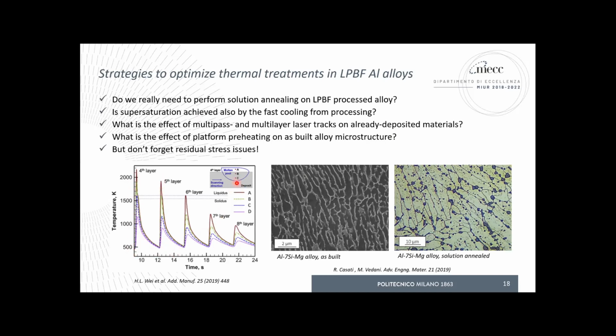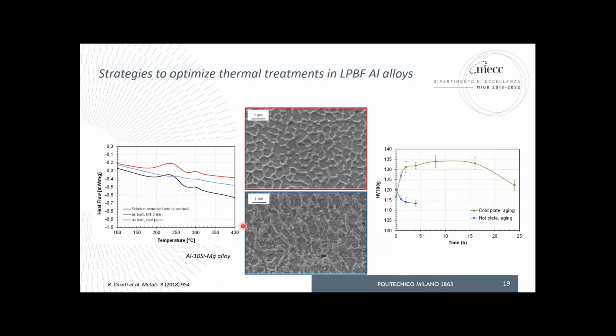For instance, the reference point here in the schematic will feel its own melting track cycle, will cool down, but then there will be another laser track very close to its own position, inducing a lower but still significant heating cycle, and then again and again, and then this will be repeated for the following layers. So I shall add some more powder, and then melt it again and again, so that there is a very complex combination of cycles. The big question is, what is the result of those cycles on the microstructure and on the precipitate condition? And then again, don't forget about residual stresses. Just to give you a few answers, and then we can stop maybe.